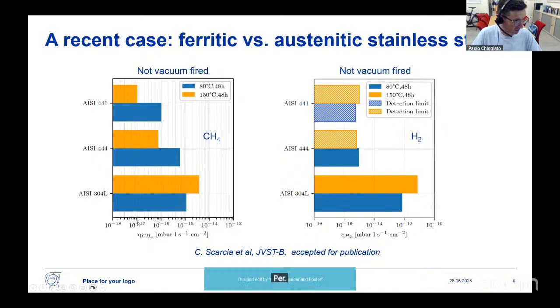Okay. Of course, all this has to be done measuring the background before, and then subtracting the value of the gas. The same has been done with the CH4. And with the CH4, the background level is much lower. And you see that we can measure values of something like 10 to the minus 17 millibar liter per second. So the order of a few hundred molecules of methane released per square centimeter per second. Okay, this is the way we do it in general.